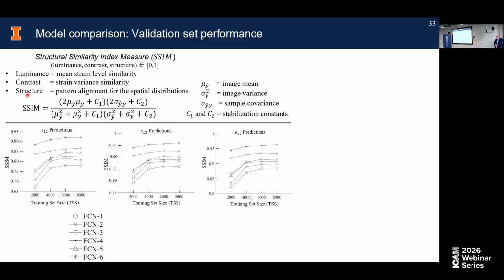But I'll show you some of the other metrics as well. A lot of what we do is based on this SSIM. This seems to work pretty well. So here's a median result, from the whole data set. The three strain components, well, you can just concentrate on the dominant one, which is epsilon 2 in uniaxial tension. So SSIM, best value is 1.